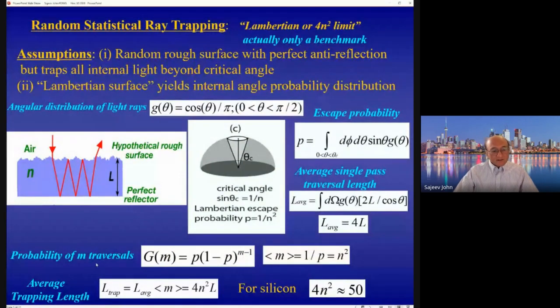Then you could ask, what is the probability that light makes a certain number m of bounces within the structure before it escapes? Well, for it to have m bounces, it would have to not escape in the first m minus 1 bounces, with probability 1 minus p, and then escape on the mth bounce with probability p. So this function then gives the probability distribution for the number of bounces. And with respect to this distribution, you could calculate the average number of bounces. And this, again, is an elementary calculation. It gives 1 over p, which, according to our previous calculation, is given by n squared.